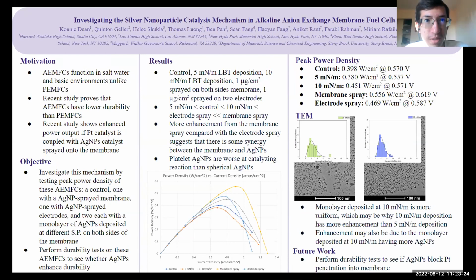Now for the results. We've tested 5 nanoparticle deposition scenarios so far, including a control, 5 and 10 millinewton per meter monolayer depositions, a membrane spray, and an electrode spray. As you can see in the bottom center, in terms of maximum power density, the 5 millinewtons per meter surface pressure fuel cell performed the worst, followed by the control, the 10 millinewtons per meter, the sprayed electrodes, and finally the sprayed membrane, which performed the best.